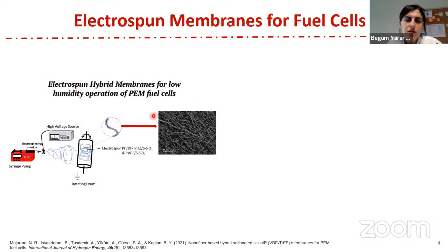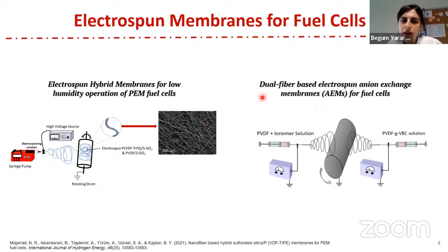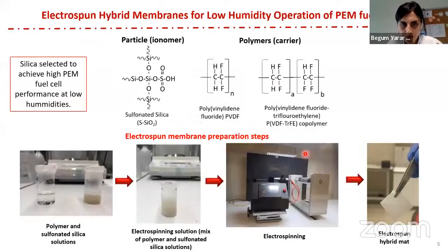The first one is we are developing electrospun hybrid membranes for low humidity operation of PEM fuel cells. Here is one example of an SEM image of the nanofiber structure. The other project is dual fiber-based electrospun anion exchange membranes for fuel cells. We are using a double-sided electrospinning setup. We are using PVDF and ionomer solution from one side, and PVDF grafted vinyl benzyl chloride solution from the other side, and we are producing composite membranes at the end of this electrospinning process.